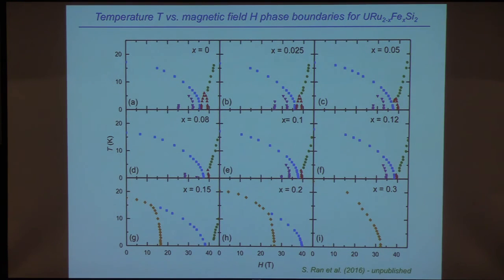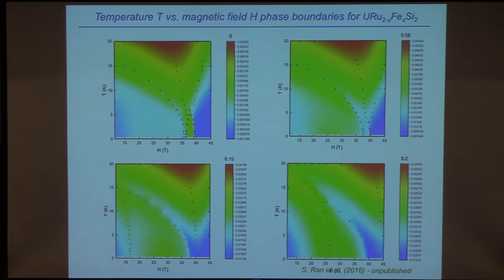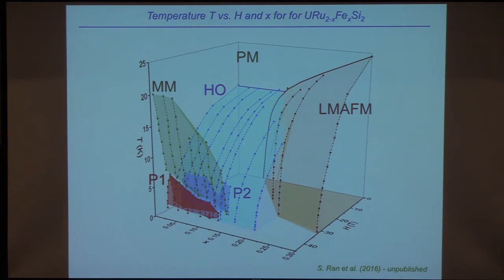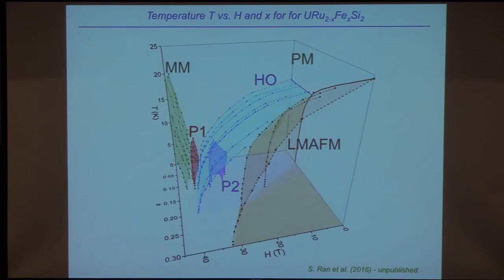We're in the process of trying to study this in more detail, and so these are some false color plots showing some of these lines, and these colors represent the value of the resistivity. They make nice figures, but they're not so easy to understand. But you can also construct a three-dimensional phase diagram. This is temperature, iron concentration, magnetic field, and so you see over here is hidden order being suppressed as you increase the field. Iron concentration is increasing this way, and then you see that you get large moment antiferromagnetism, and as you apply field in this range, you suppress that, and then hidden order grows out of it, and then you see the metamagnetic transition feature here, and then some other features due to the other quantum phases. This is just another view, showing you these quantum phases in here.